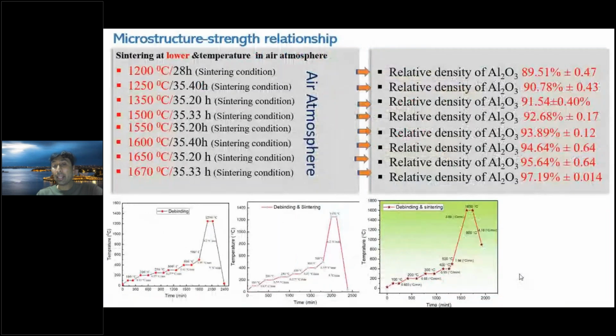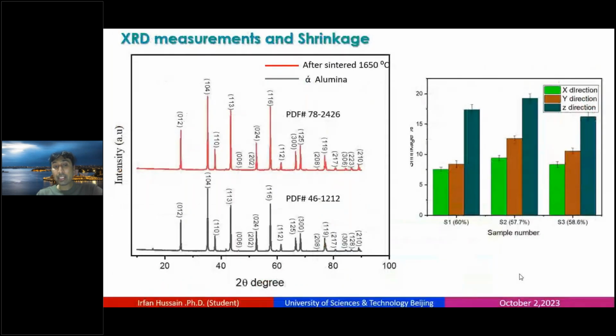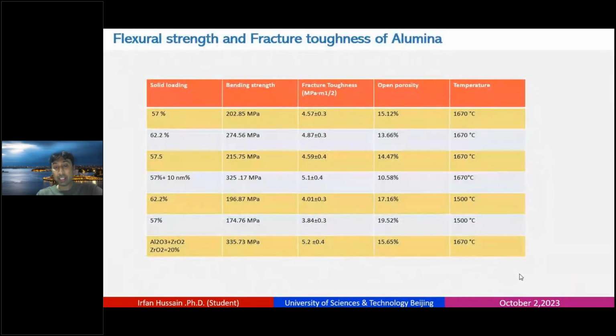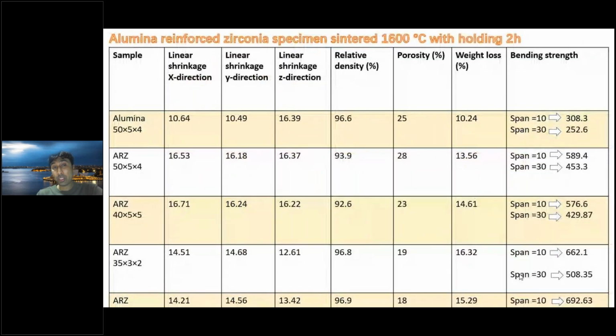So after sintering at the high temperature of 1670, I got a high density of 97.19. Here, after 1650, we also found there is no phase change, and here is also the shrinkage rate. So here are the flexural strength and fracture toughness of the specimens of different compositions. At 57% the fracture toughness is 3.84, and with the addition of zirconia, the fracture toughness is enhanced to 5.2. And here is the alumina reinforced zirconia specimen sintered with two holding times. So here you can see, for example, with the span distance, the flexural strength is increased.